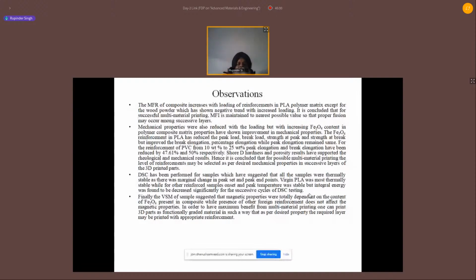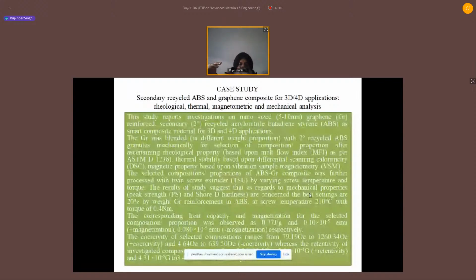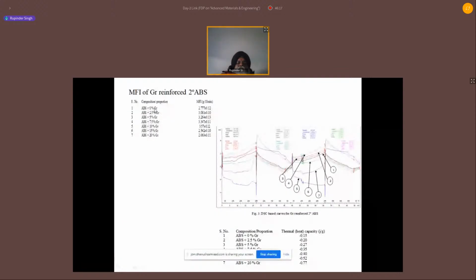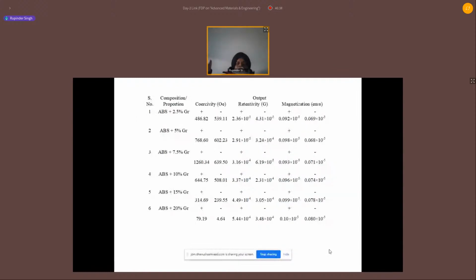Right, so similar to this, we try to reinforce different types of material into the polymer matrix. Like in this particular case, we reinforced graphene into ABS, and once we put different compositions of graphene into ABS, we looked at their rheological property in terms of MFI, then their thermal stability analysis, how they are behaving, and with the different reinforcement, what is the effect on their heat capacity. You can see with the reinforcement of the graphene, the heat capacity is basically increasing. And then of course we look at the effect on their magnetic property in the form of coercivity, retentivity, and magnetization.